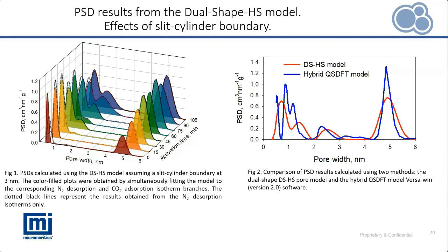Figure 1 shows such systematic variation of pore size distributions. Clearly, the micropore peak broadens with increasing activation, and the mesopore peak, which is obtained by templating method, stays symmetrical and in the same position, but showing increase with increased activation.